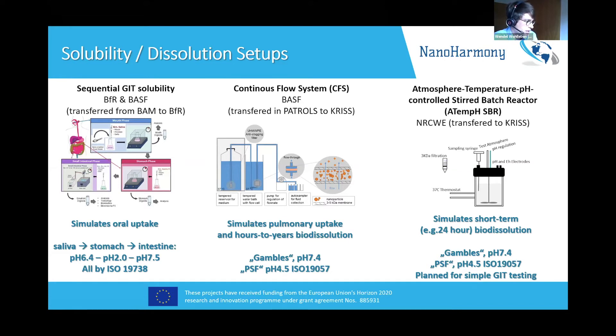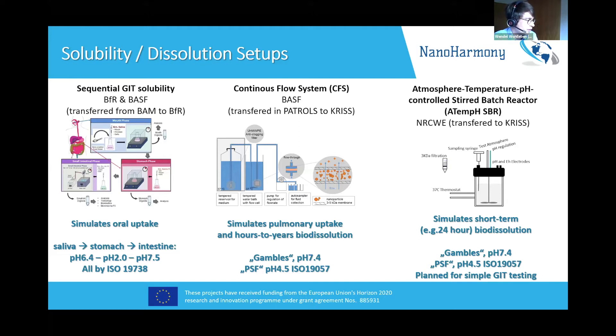The basic idea here is really the same as the one that was reported this morning from Italy. The focus here is on the dissolution of the materials, and it follows a standardized composition of simulant fluids to cover saliva, stomach, and intestine. In the middle, you see the continuous flow system, which focuses on the pulmonary dissolution conditions and is adapted to detect and compare hours to years of half-time — so relatively slower processes as relevant for this compartment.